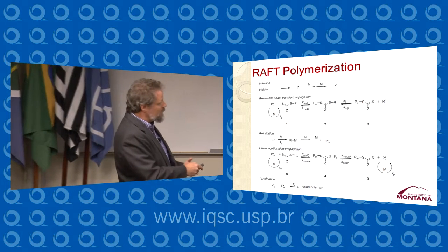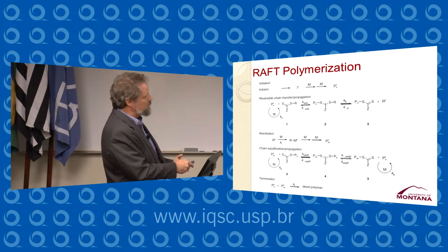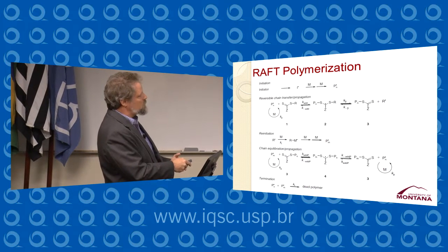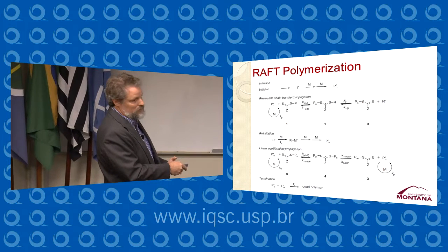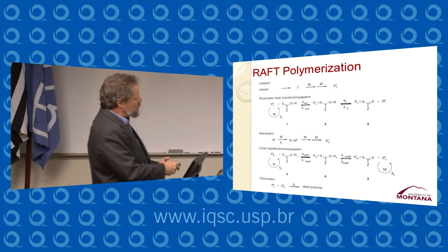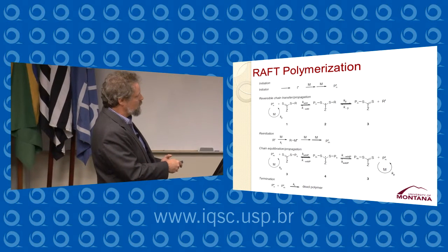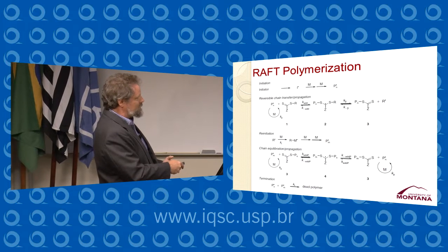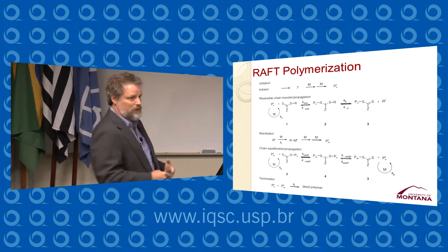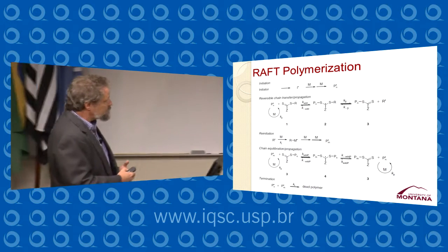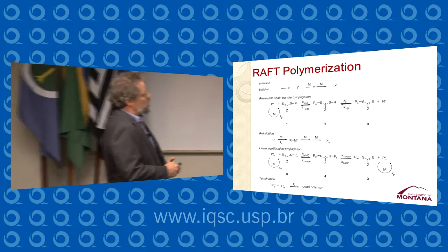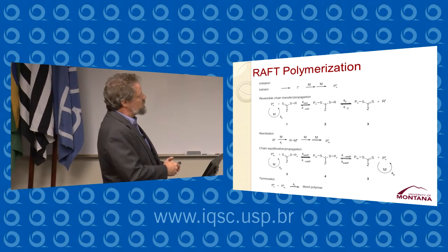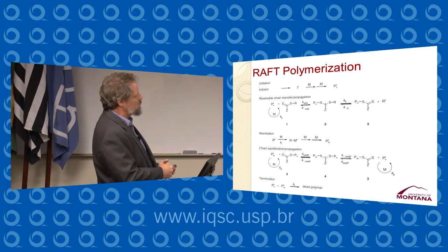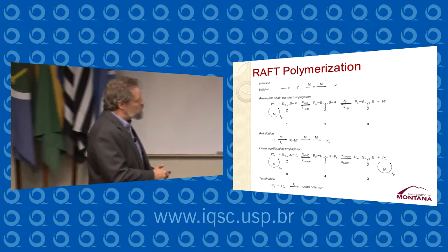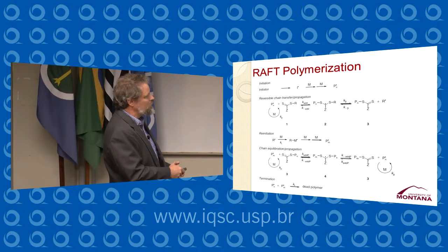It can then release that leaving group, which is a free radical. That leaving group, which is released, can initiate additional polymerization. The number of these polymer growing chains here, these chains initiated by this leaving group, is equal to or less than the original concentration of the chain transfer agent. We use a very low concentration of initiator and a relatively high concentration of the chain transfer agent. So most of our polymers are in this form, initiated by the R group and capped on the end by this chain transfer agent.